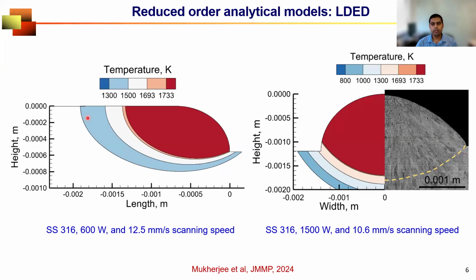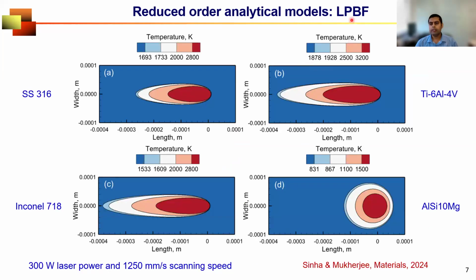So this is an example of laser-directed energy deposition additive manufacturing, where you see a very primitive reduced order analytical model can more or less predict the molten pool or deposit dimensions within acceptable limit. For laser powder bed fusion, and this is from a recently published paper with my student, you can see that they can capture not only the effect of process and process conditions, but the differences in the materials. So A, B, C, and D are for 4 different materials: stainless steel, titanium alloy, nickel alloy, and aluminum alloy.